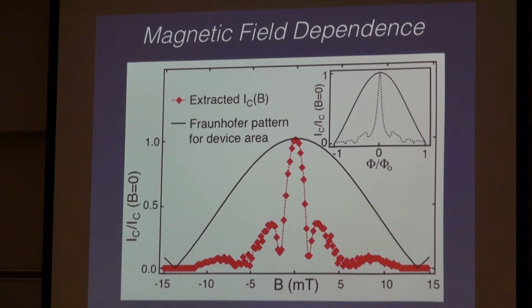Here's what you get for the Fraunhofer pattern of the Josephson junction. And this isn't just one device. We measure many devices that look like this. In black is if you take the device area and include the penetration depth of the superconductor, you should expect a Fraunhofer pattern that looks like this. You can see 2 features that are important. One is that it's substantially narrowed with respect to this expected Fraunhofer pattern. And then the other thing, perhaps more interesting, is that this first 0 is elevated off, it has some finite critical current associated with it, whereas the second 0 and maybe the third 0 don't have this.